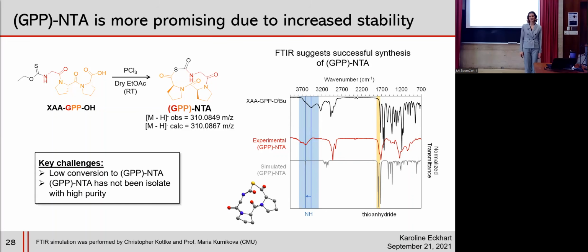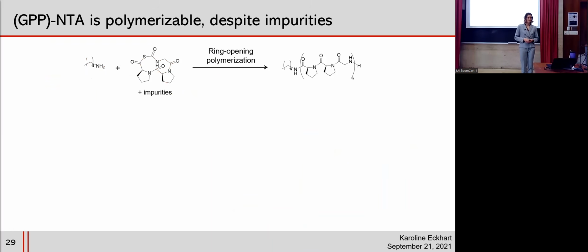But there were still some challenges with this synthesis, mainly that there was low conversion from the linear starting material to the macrocyclic NTA, and that it was very difficult to purify, and we were actually not able to purify GPP-NTA successfully. Nevertheless, we went forward with a proof of concept polymerization in the presence of the impurities just to see if this molecule would actually ring open to form a collagen mimetic polymer.